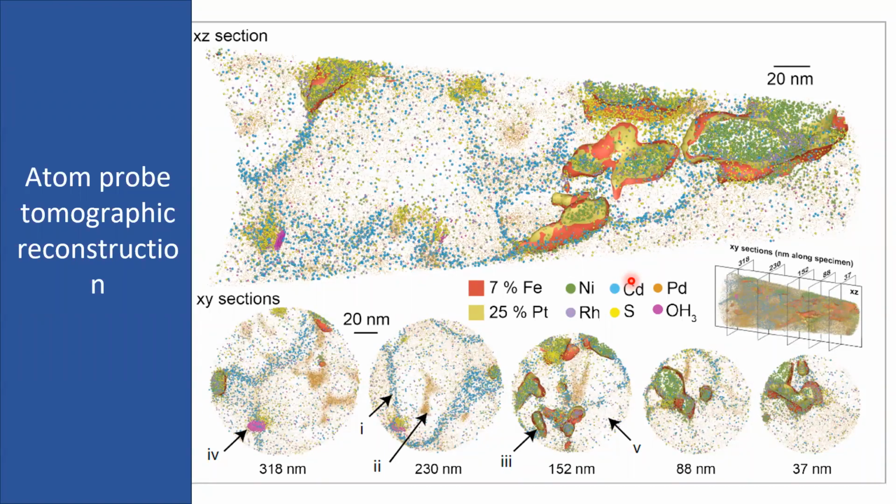This ran really well. So basically with atom probe, what you're doing is you mount the needle, you pulse a laser towards it while it's in an electric field with a voltage across it. And basically the laser bashes off the atoms one by one. They go off into a time of flight spectrometer. And by measuring what the atoms are, how long it took to get there, you can actually say not only what they are, but where they came from, and you can do the 3D reconstruction.